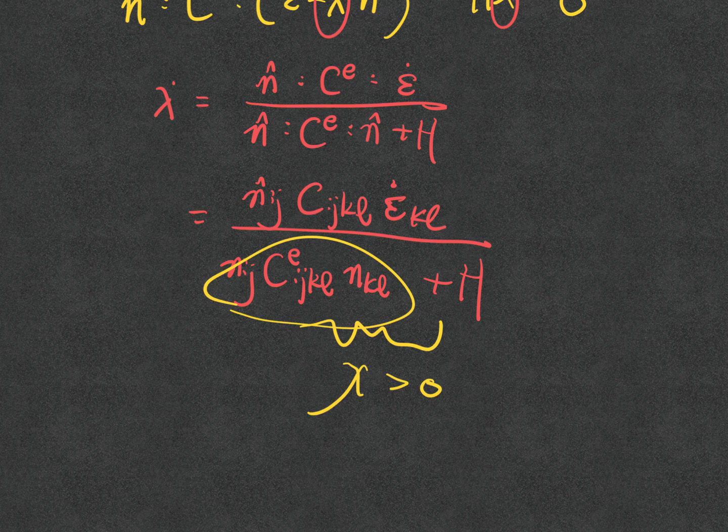If this becomes negative, then what happens? I just want to challenge you to connect the mathematics to the physical world so you know what you're doing. With this term, if your H is so horribly negative, super negative, then the whole thing could become negative.